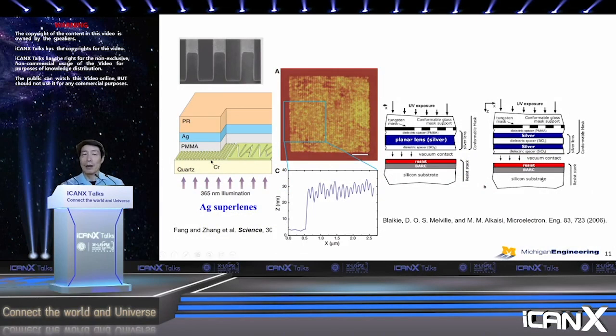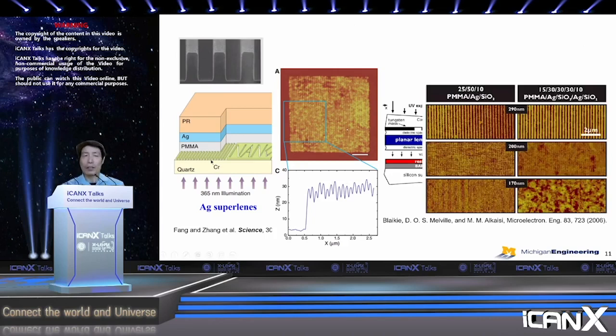Okay. But you will see some difference from this ideal structure people want to have in manufacturing. This is something you need to have in order to use it for a practical purpose. First of all, you see this is using an AFM image. Right? The pattern features are very shallow, maybe up to 20 nanometers deep. Okay. And on the right-hand side, you can see the lateral scale is probably less than 10 micron. Right? Even within 10 micron, the patterns are very non-uniform. Again, these are not going to be very useful for practical purposes.